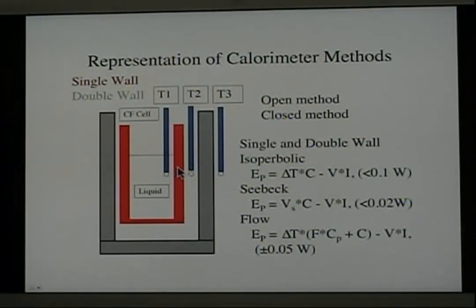Nevertheless, this is a problem that can be solved by using a second wall, or a double wall isoperibolic calorimeter. Here, a wall outside of the electrolytic cell is used to measure the heat flow by measuring the temperature on the inside of that wall and again on the outside of the wall. The temperature difference across the wall then is a measure of heat flow through this material. And you'll notice that the temperatures are now independent of what's occurring within the cell itself.